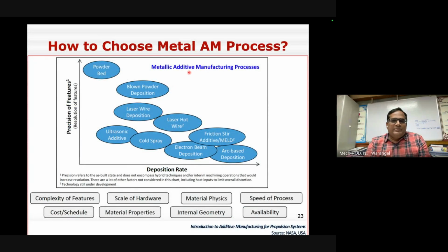And then how do you choose your metal AM process? So that is your precision, or rather your resolution versus deposition rate. So your powder bed will give a better resolution, but the deposition rates are very low. But on the other hand, like arc-based deposition or friction stir additive, you have huge deposition rates, but the precision or the accuracy is very low. You can make only near net shaped parts, but your deposition rates are very high. But anyway, we need to compromise. You have a trade-off between your precision and the deposition rates.